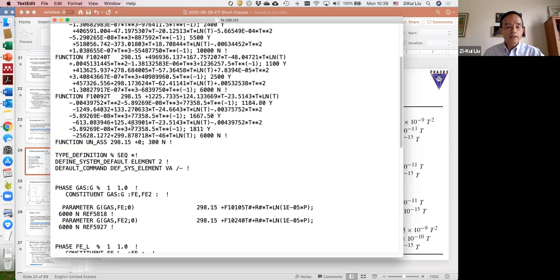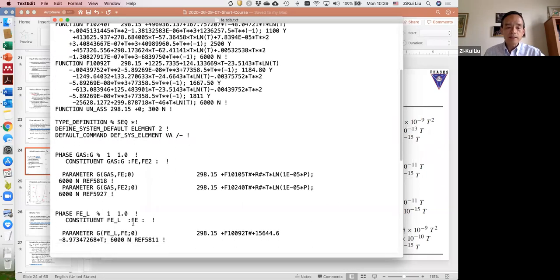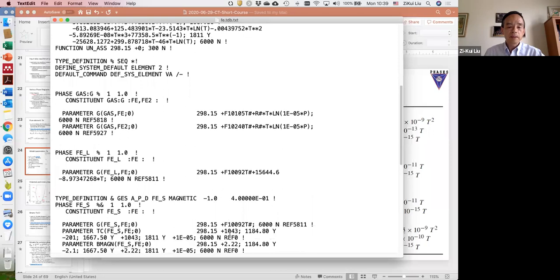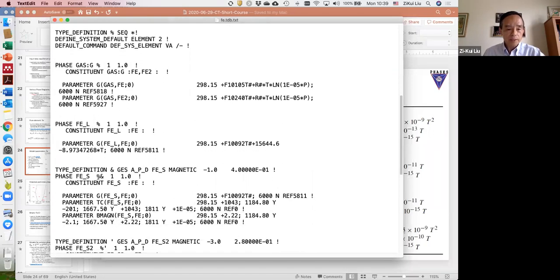And so for the gas phase you have 2 species. The liquid is only 1 species. So you have one free energy plus 2 terms. So that one is for the solid phase. So then you have the FCC phase, the BCC phase.